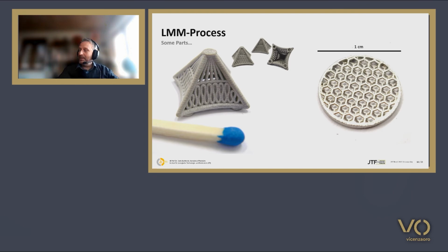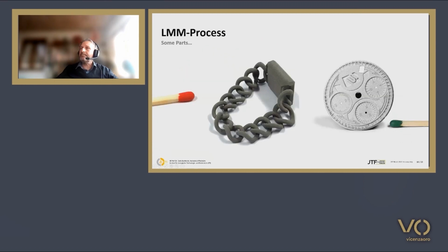So I would really have liked to come there and have a box of these materials with me to give you a real representation. You can make fully functional parts, though. This ring with this chain here was printed in one bit, and after sintering, the parts will stick together a bit. But they are not sintered together, so with a little bit of mechanical pressing and pushing, you can make it fully operable, so that you have a stainless steel chain that has really no connections. Nice gimmick. This watch case you've seen before, and again you see that a very, very high detailed resolution is possible. You see the matchstick here for comparison.